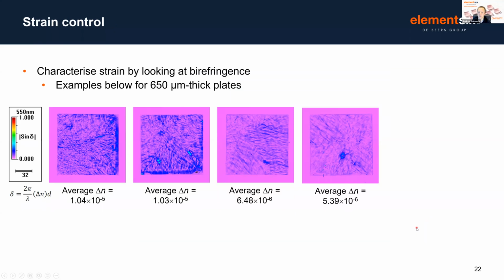So we talked about strain earlier, so we need to start looking at the strain in this material clearly to get an idea of whether it will be highly performing or not. So what I show here again is optical birefringence images of this sort of diamond material. The good news is that the birefringence levels are at or below that critical 10⁻⁵ level that we identified earlier as being detrimental to the coherence time. So optical birefringence gives us an initial suggestion that this material would be very highly performing.